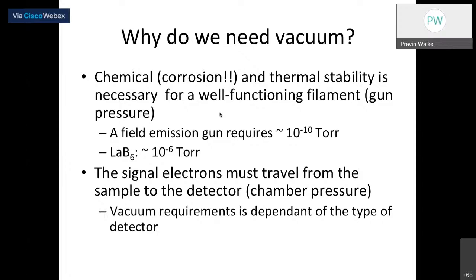Also, as soon as the electron gets detached from that particular electron beam, it has to travel through the sample to the detectors. So that electron should not get deflected by external entities, and therefore this should be in a vacuum, right? So a field emission gun usually requires 10 raised to minus 10 torr of vacuum pressure inside the chamber. Especially this field emission gun requires more vacuum as compared to a lanthanum hexaboride tip, right? So lanthanum hexaboride requires 10 to the minus 6 torr of vacuum inside, right?